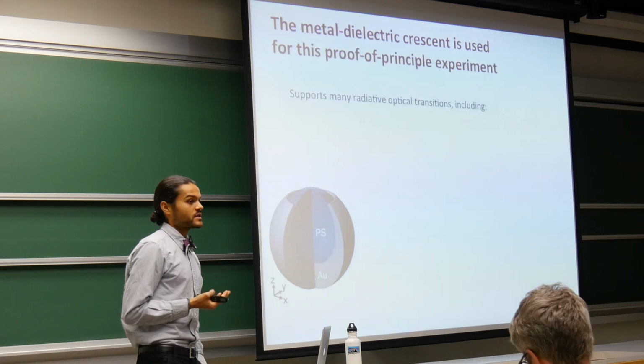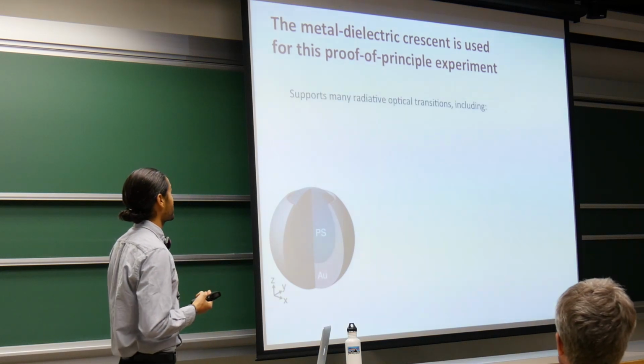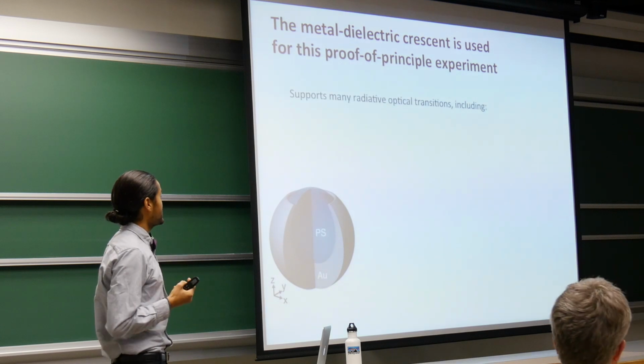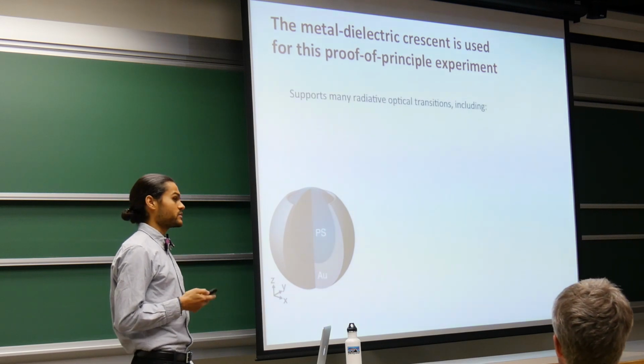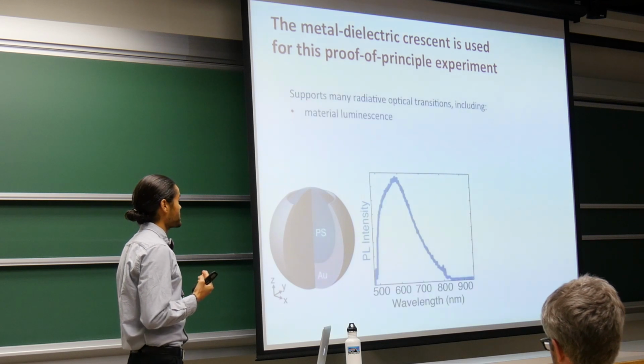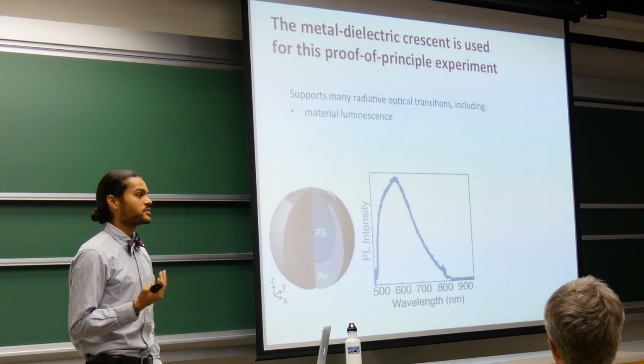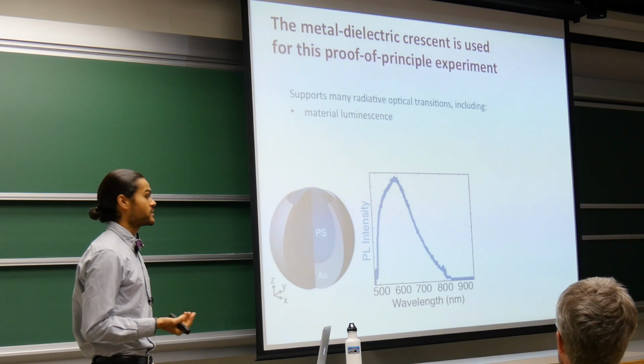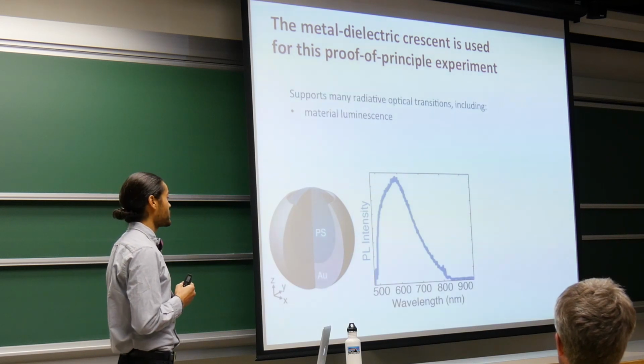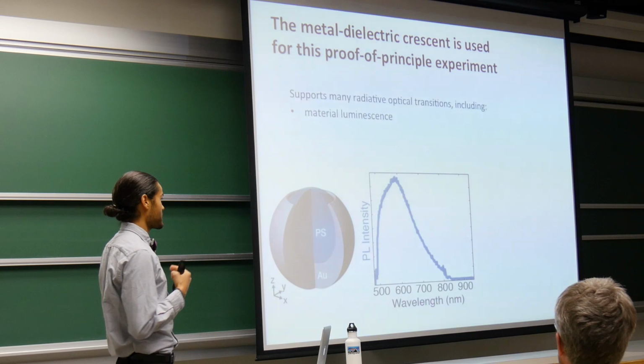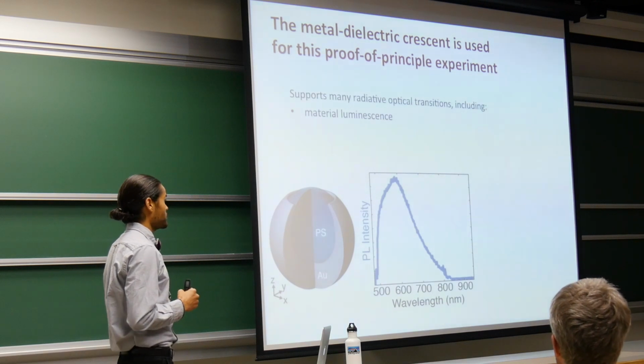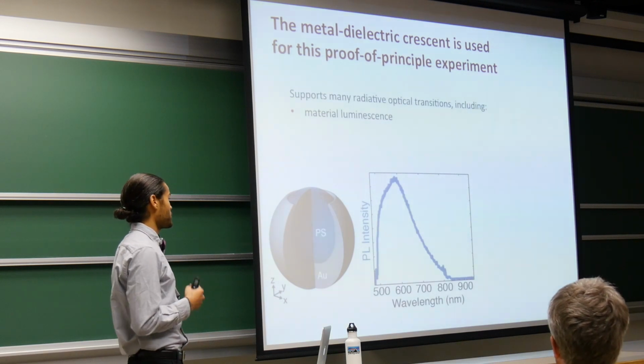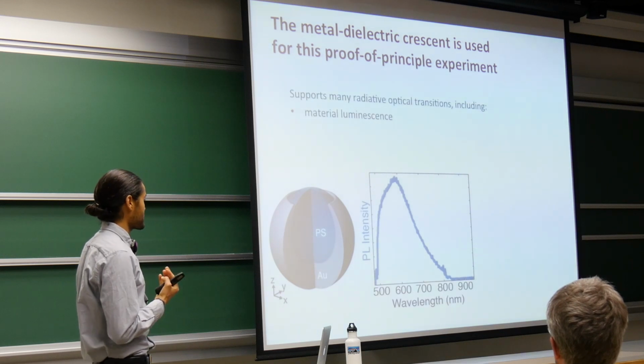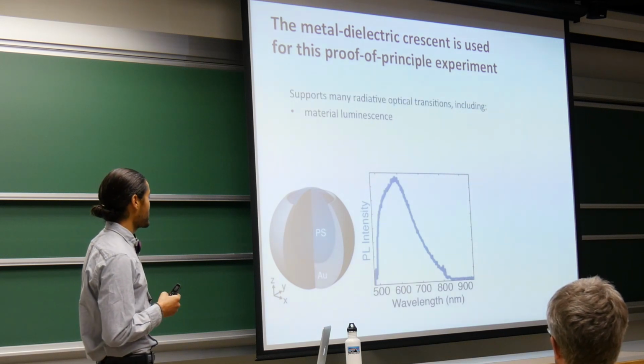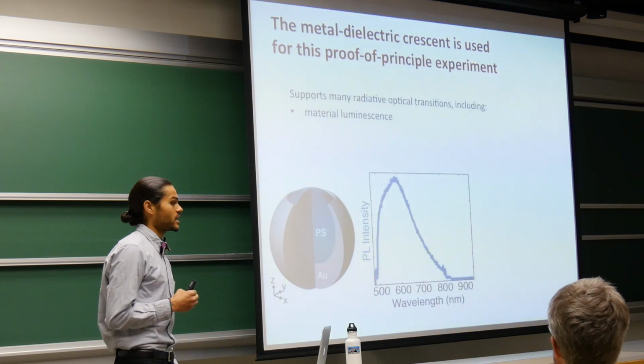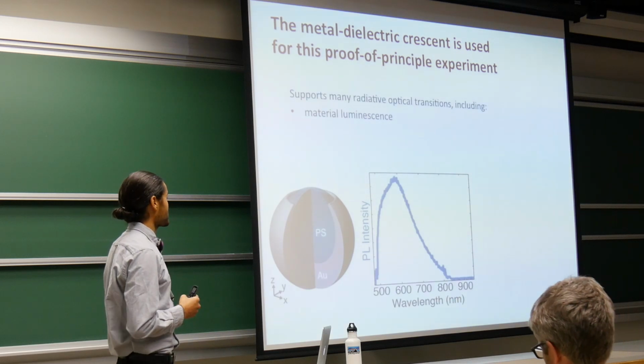As I mentioned, the other reason why this particular structure is great for our proof of principle demonstration is that the crescent supports many radiative optical transitions. One that I haven't mentioned yet is material luminescence. Most people don't think of metals as great emitters, but it turns out that when you nanostructure gold in particular, because of the interband transitions that are accessible with light in gold, you can get a lot of light out of gold if you pump it. So here we're pumping our gold crescents with a laser at 488 nanometers, and we can see this really broad peak corresponding to these interband transitions in gold.